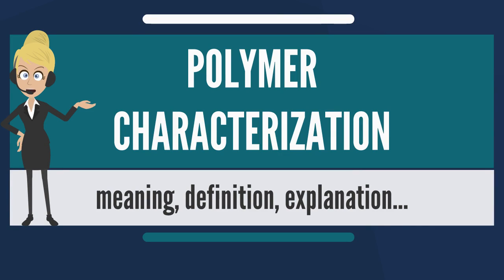Molar mass determination of copolymers is a much more complicated procedure. The complications arise from the effect of solvent on the homopolymers and how this can affect the copolymer morphology. Analysis of copolymers typically requires multiple characterization methods. For instance, copolymers with short-chain branching such as linear low-density polyethylene, a copolymer of ethylene and a higher alkene such as hexene or octene, require the use of analytical temperature-rising elution fractionation (ATREF) techniques. These techniques can reveal how the short-chain branches are distributed over the various molecular weights.